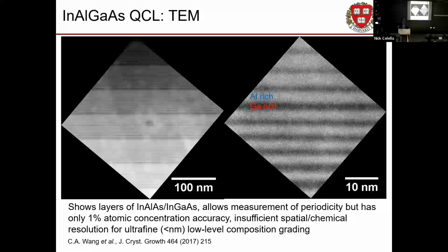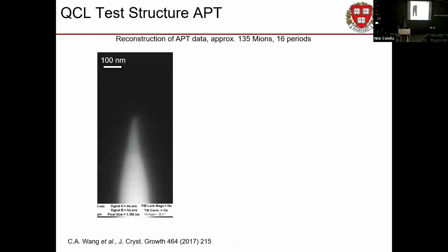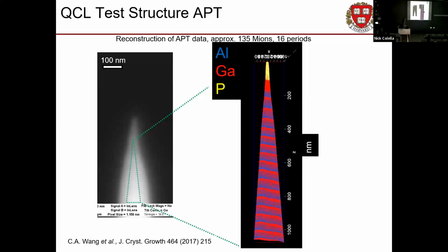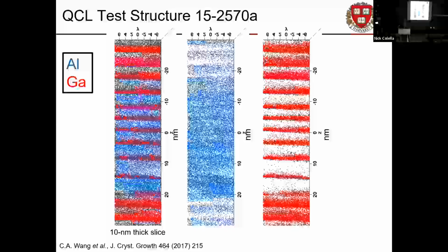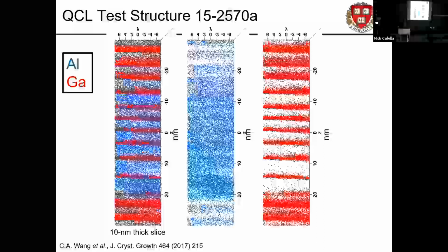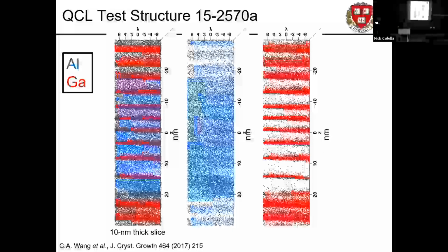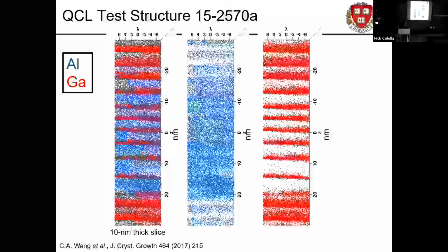And once again, we put it in the TEM and it looks okay. See all the little atomic planes in it, they look about as they should. There's no discontinuities, no dislocations, whatever. But we throw the atom probe at it, and we look real close in, and we can see all these periods they tried to grow with different elements. And you notice anything different about one edge of this red stripe versus the other? Yeah, one side's all sort of raggedy.